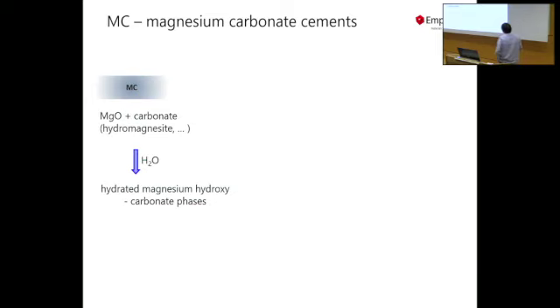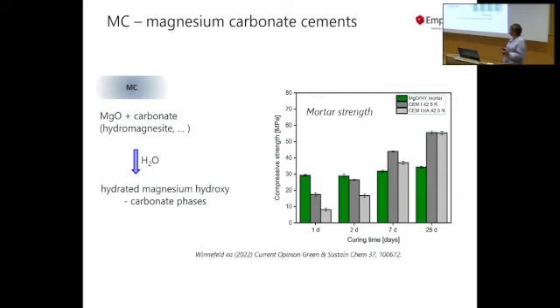So now we go back to the cement after I tried to explain that we can find the magnesium. Magnesium carbonate cements are basically based on mixing magnesium with a source of carbonate and water. The source of carbonate can be already a magnesium carbonate, for instance hydromagnesite or nesquehonite, or it can be bicarbonate or carbonate solution. If you do that, you start to make something which we called, until very recently, hydrated magnesium carbonate phase. Basically, we didn't know what it was, but at the same time, you also get a compressive strength on mortars of around 30 megapascal after 1 day.